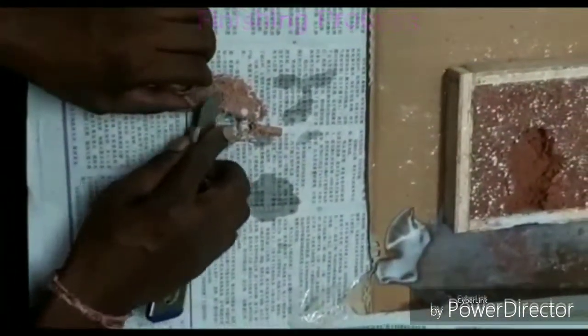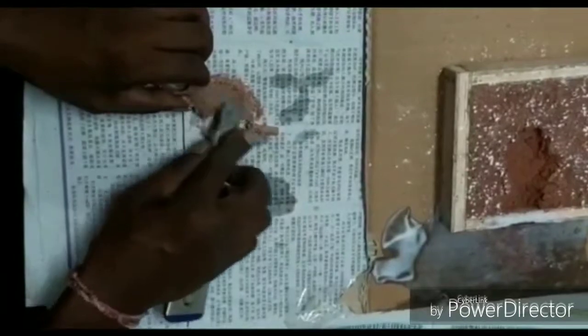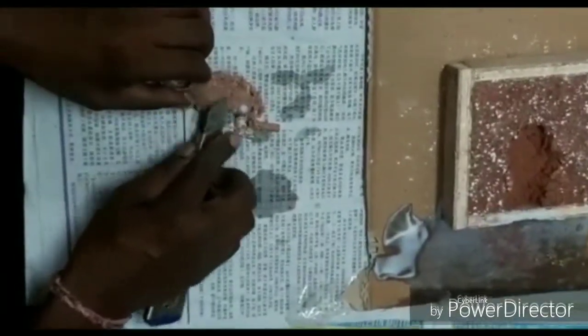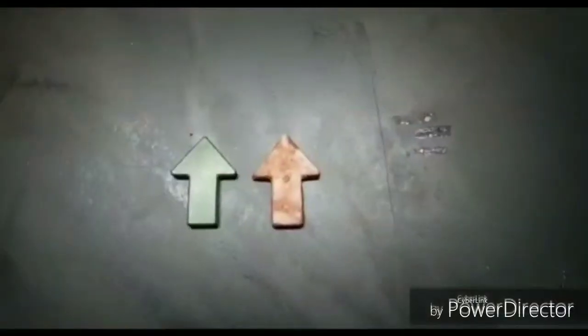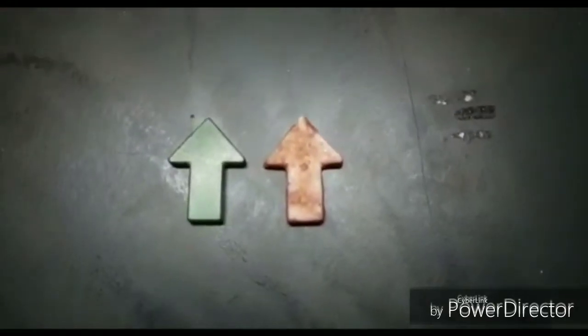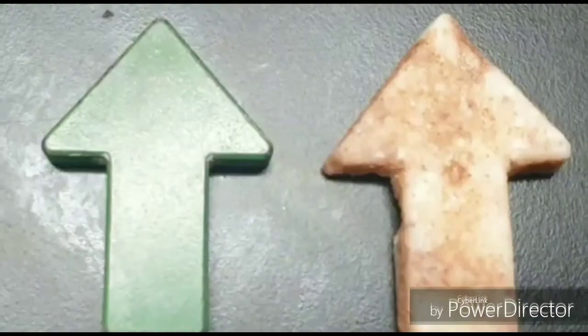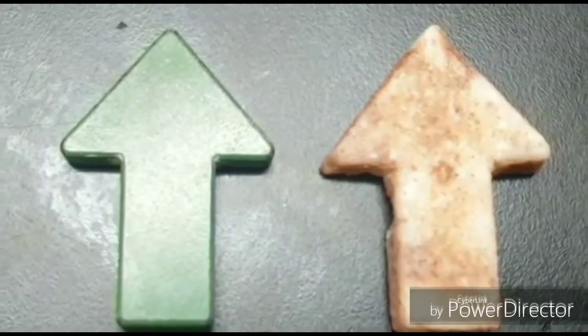The core and flask still have some minor gap that causes flash buildup at the side of the product. We have removed quite an amount of sand grains during the finishing process to get the desired shape.